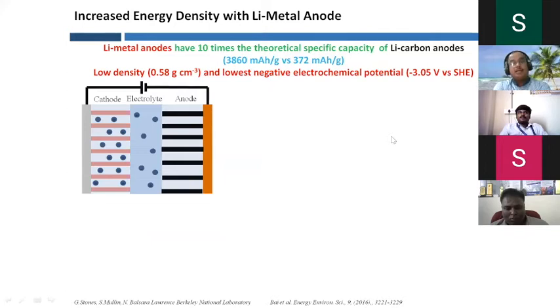Lithium metal is the ideal choice because it has 10 times the theoretical specific capacity of lithiated carbon. Lithiated carbon is something around 372 milliampere hour per gram. But if you are able to use lithium metal instead of lithiated carbon, we can think about reaching theoretically 3,860 milliampere hour per gram. So in this case, it is 10 times, from 370 to 3,860. And much more, lithium metal has low density and the lowest negative electrochemical potential, minus 3.05 volts.